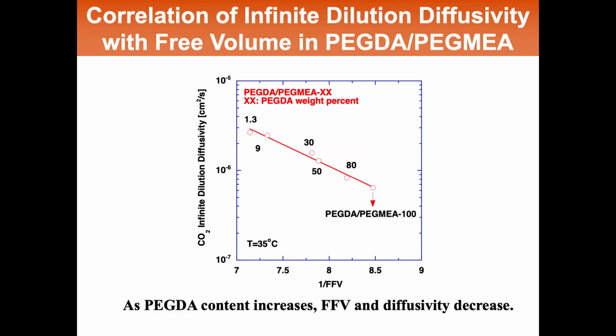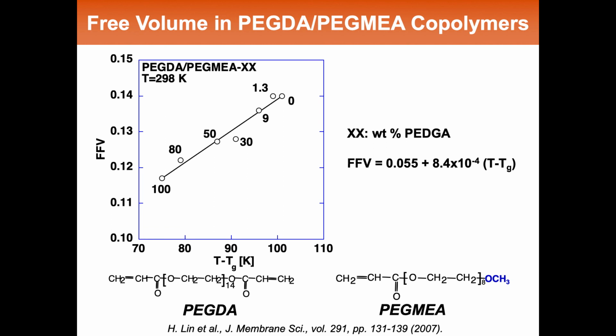And we actually cheated a little bit on that in the sense that if you look at the structure of these two components that are going into this mixture, and you were to calculate on a weight basis what is the weight fraction of ethylene oxide units in this monomer and in this cross-linker? They're both about 85 weight%. And so as you make mixtures of these two, across the entire composition range, you're not really changing the chemical composition of the polymer so much. Now, if you picked different length cross-linker or different length monomer, that would not be the case. And that was why these were picked this way, to be able to change the network topology without changing the chemical composition. It was one variable at a time.